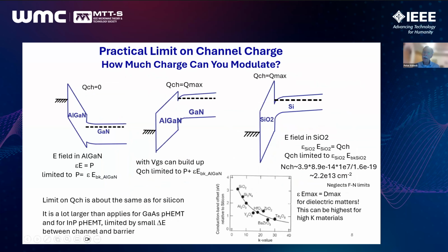I should note, however, that there's a practical limit to how much polarization charge you would wish to have for the 2D electron gas, because after all, in a FET, you have to turn that charge on and off by application of the gate. The electric field that is established to modulate the charge is limited both by the breakdown electric field of the dielectric material that you use, and perhaps by Fowler-Nordheim tunneling. So, in fact, in the case of silicon, the limits on the charge density that you can obtain are also on the order of 10^13, or even a little bit higher.